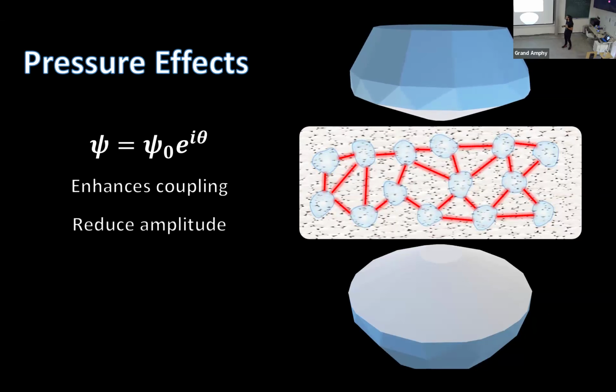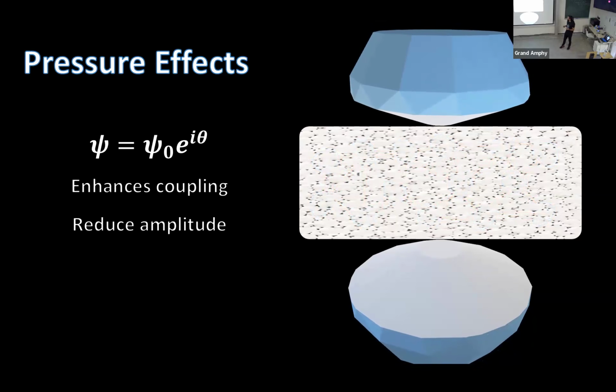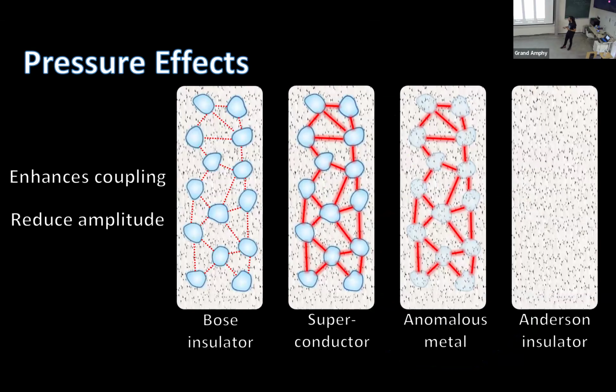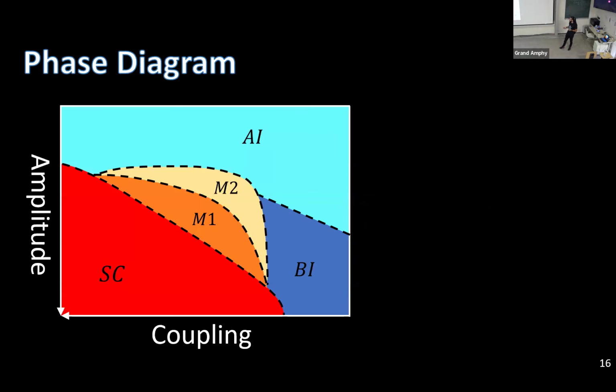As we continue increasing the pressure even more, we're reducing the amplitude within each grain, and thus we're destroying superconductivity in each one of them, and so superconductivity in the global system, up to a point where we destroy superconductivity altogether, and we're left with a normal Anderson insulator. And we think one of the most unique things is that in between this transition, where we increase the coupling and reduce the amplitude, we discovered this anomalous metallic state that had never been seen in indium oxide. This led us to propose our phase diagram, where we have those two competing effects, the coupling and the amplitude of our system, and the different phases.